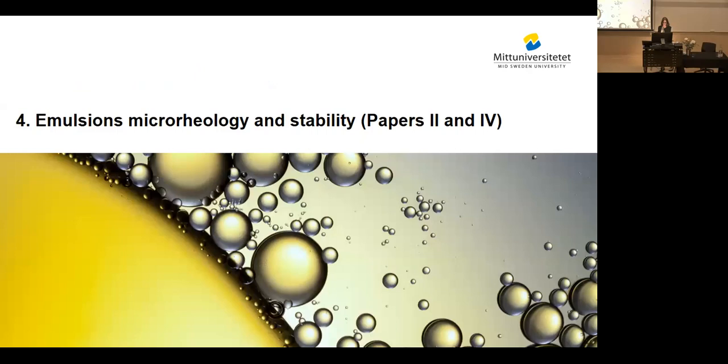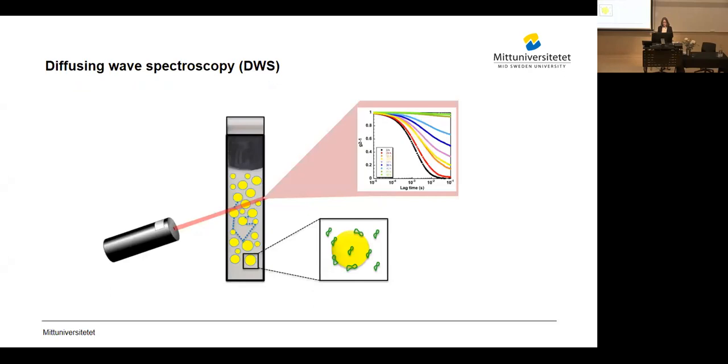Now a few highlights on the emulsions' microrheology and stability. We have been exploring the diffusing wave spectroscopy technique, which allows for much higher frequencies than conventional rheometry, and also allows us to monitor in real time changes happening in the microstructure of the emulsions. This technique is gaining popularity in the design and optimization of, for example, pharmaceutical emulsions, because we can analyze turbid samples with minimal disturbance.